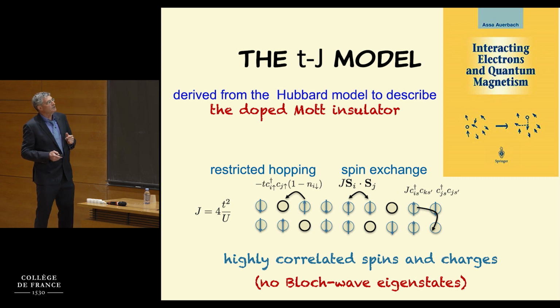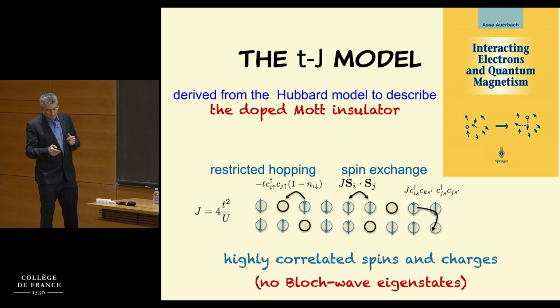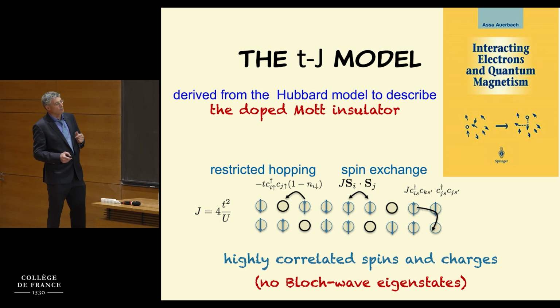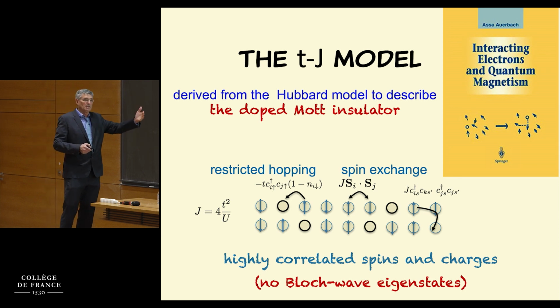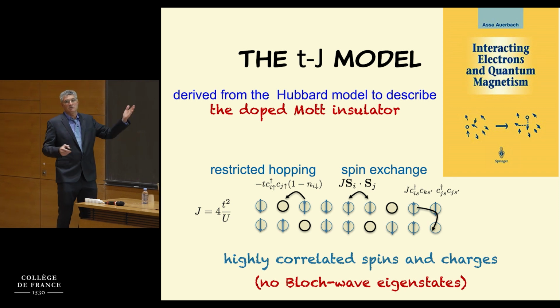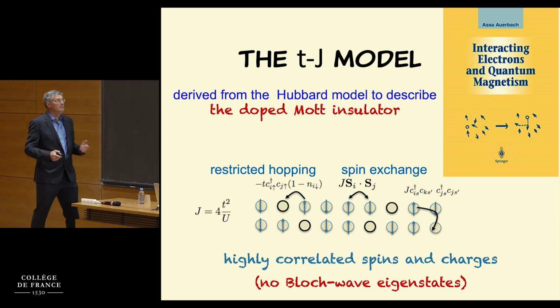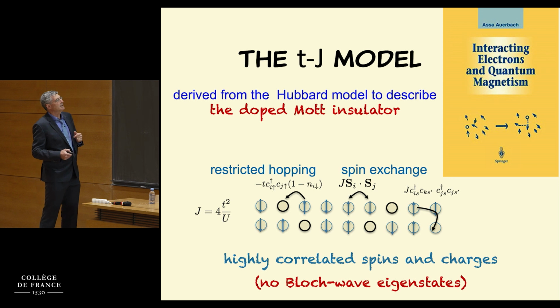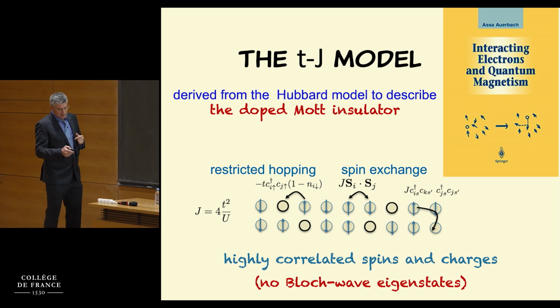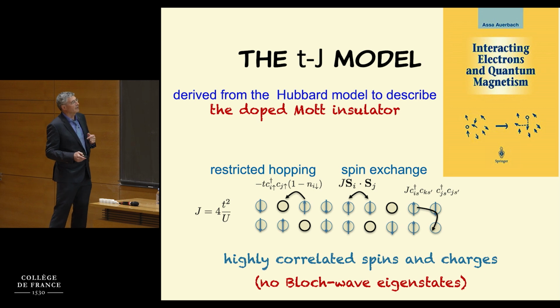So it really describes a system that is close to a Mott transition. Why? Because if you fill up one electron per site, as you can see here, if you fill up all these electrons and you don't allow double occupation, all these electrons become stuck. And this is actually in the regime where band theory tells you that you have the large Fermi surface and it's a very good metal. So getting all the charges to get stuck at half filling is called the Mott effect.